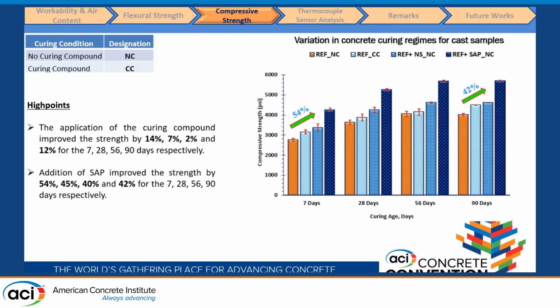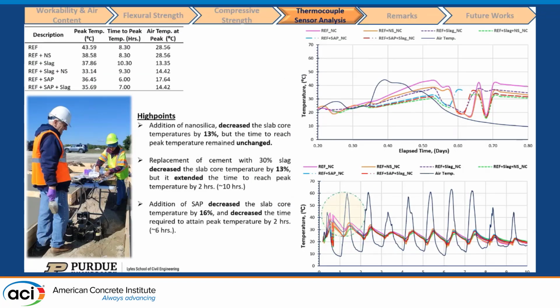Then we looked at some of the data obtained from the thermocouples installed in each of the slabs. We found that the addition of nanosilica decreased the slab core temperature by 13%, although the time to reach the peak remained unchanged. And for the replacement of 30% of cement using slag, there was also a reduction in the core temperature of the slab, but the addition of SAP decreased the core temperature of the slab by 16%, and the time to reach this peak was reduced by 2 hours.